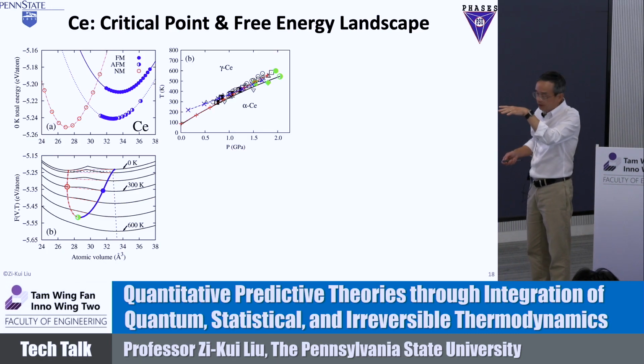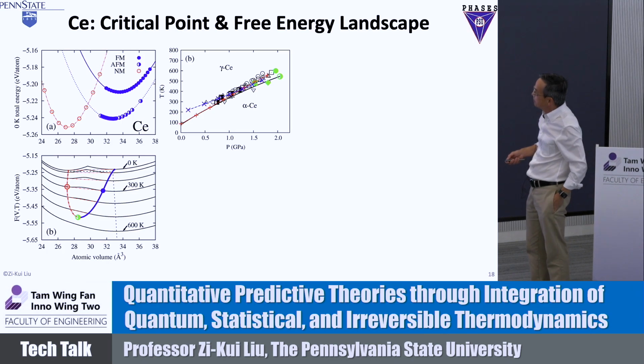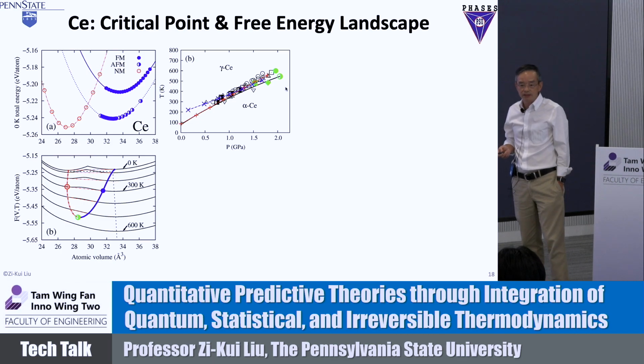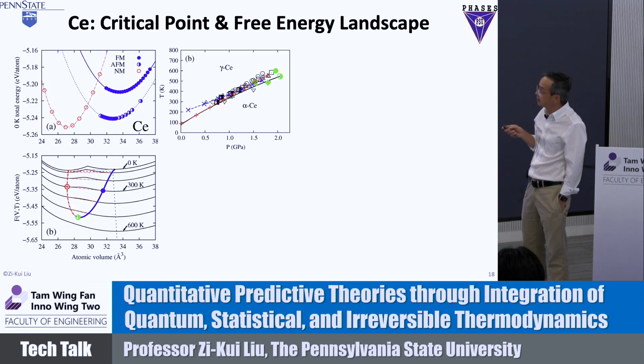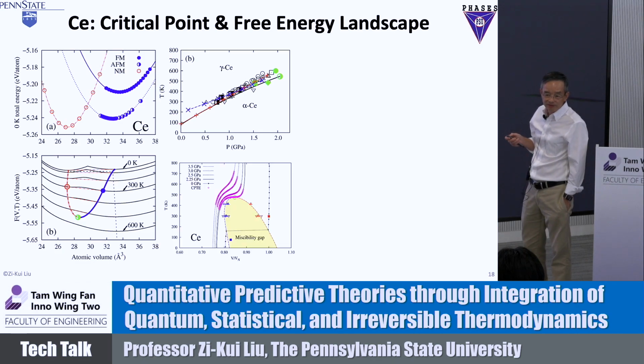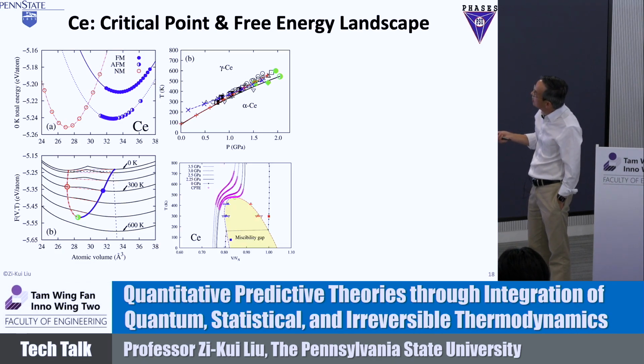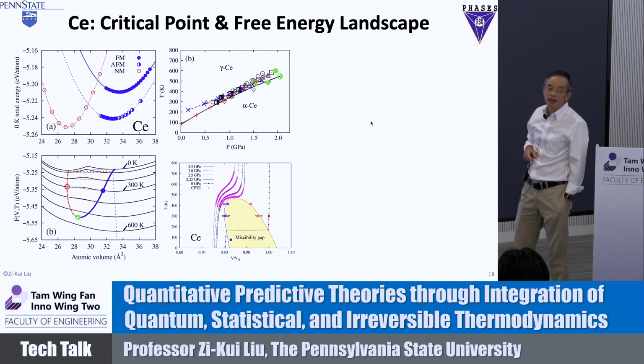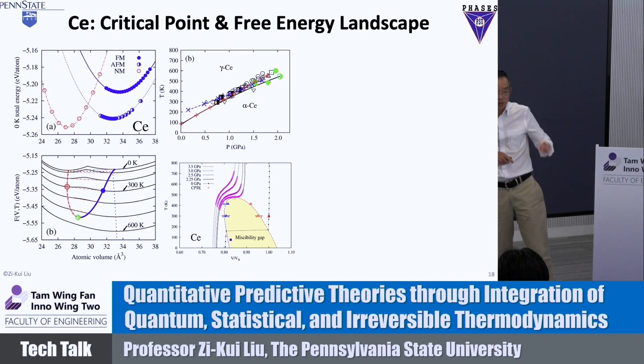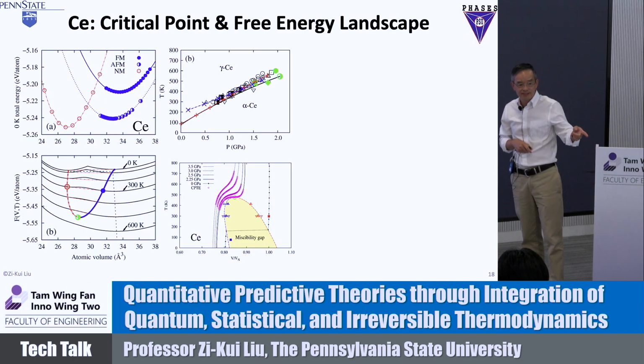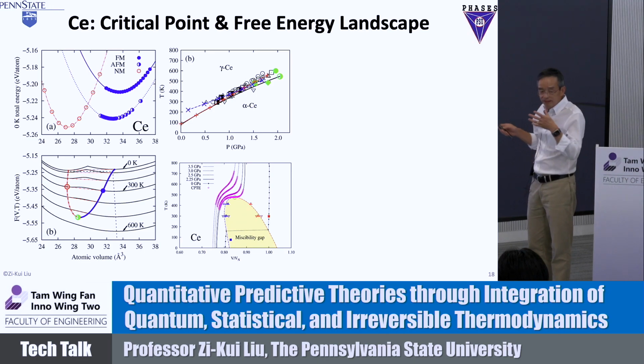The derivative gives you the pressure, so we can predict the temperature-pressure phase diagram, with the solid line as the prediction. The symbols are from experiments, including the critical point at the top here. We predicted this back in 2008, 2009. The importance of this line is that at the critical point we get the divergence of a property, a singularity. That means we can predict singularity. How do we show that? We change the pressure to volume. Then you see the slope between T and V is horizontal, inversely infinite. That means at the critical point the volume expansion becomes infinite. That's the singularity, all predicted from that.